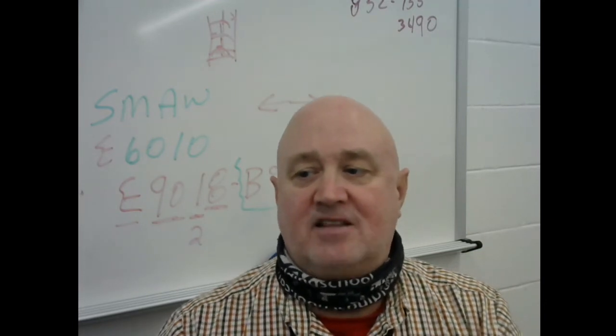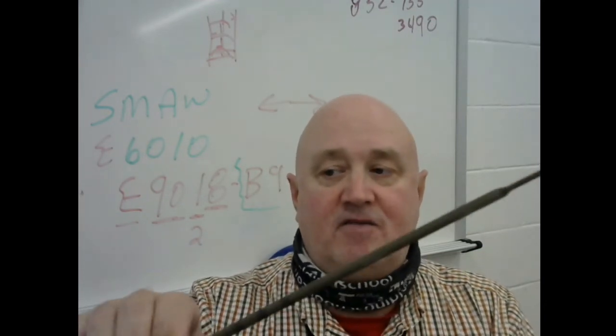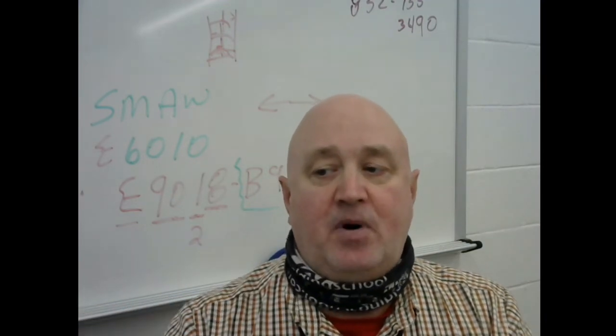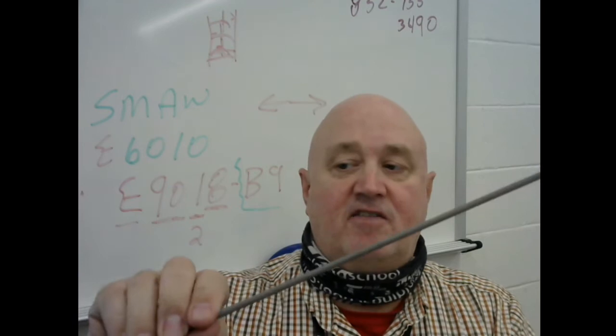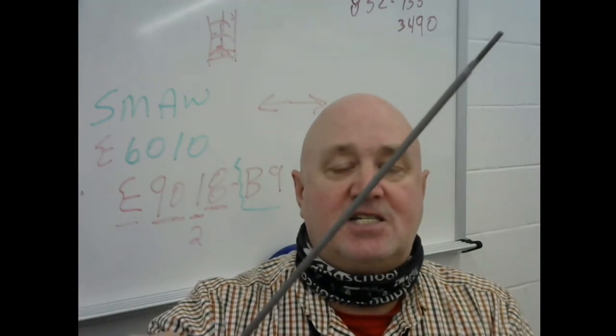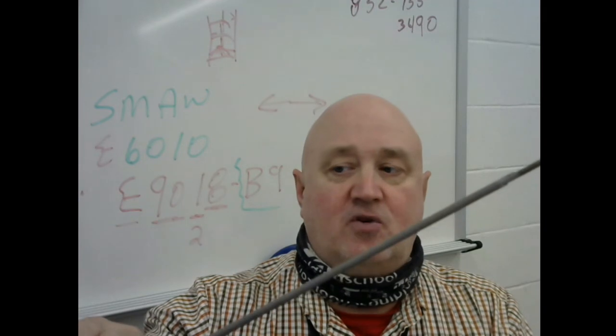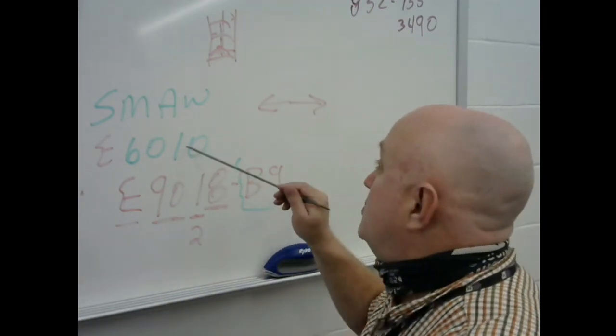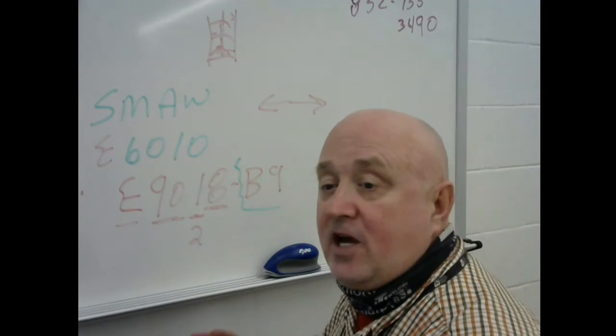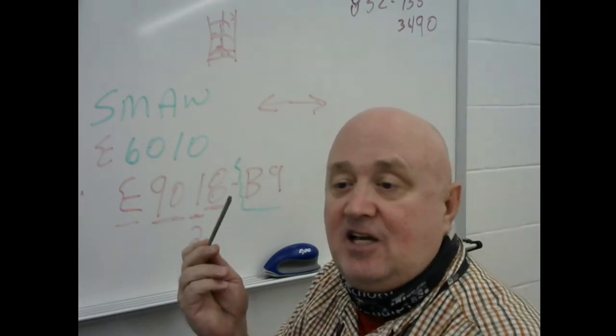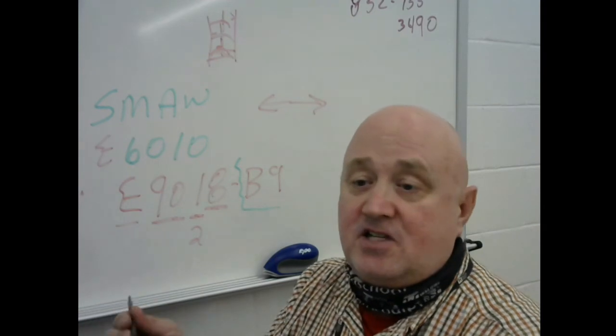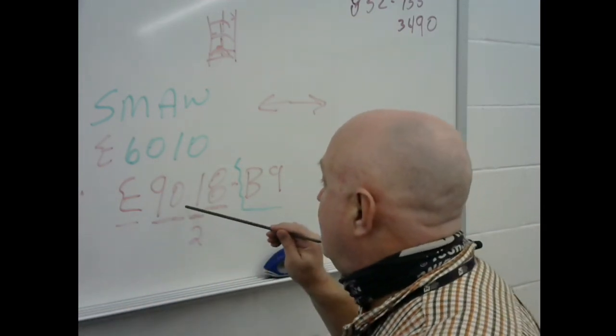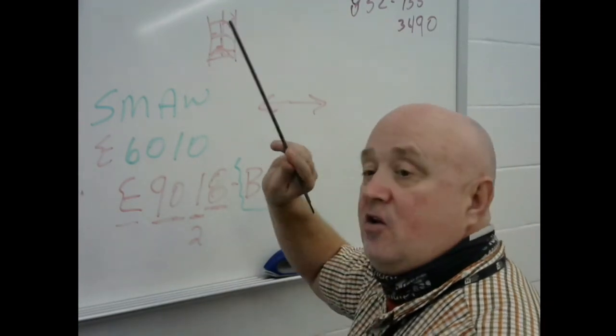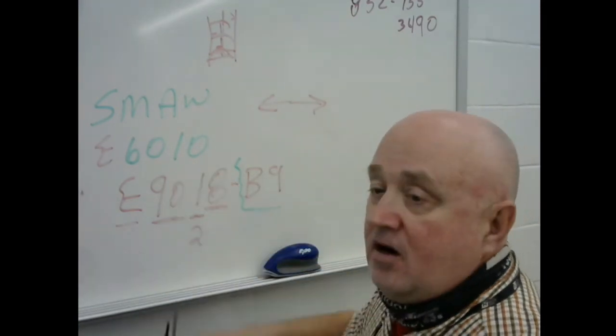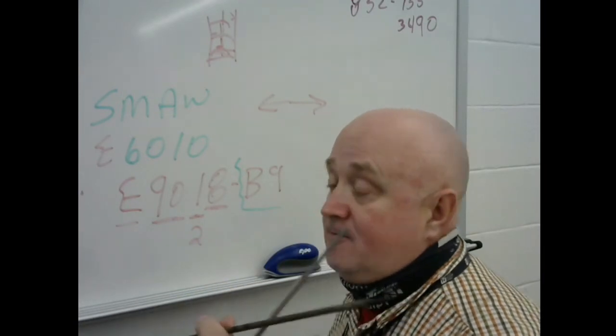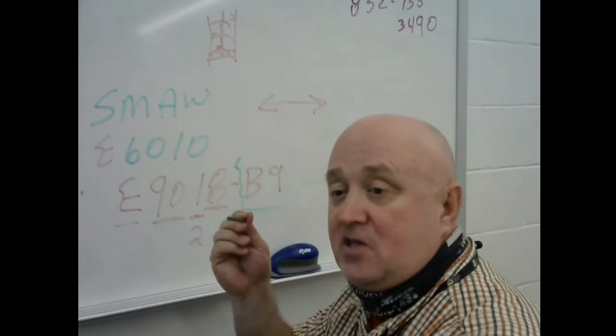It does a little bit like the 7024 where we've got some fast deposition, but it also has the characteristics of our fast freeze, which is 6010. 6010 has a fast freeze characteristic. That weld puddle, if I'm welding out of position, is going to freeze a lot quicker than something like a 7018, which is a fill freeze. And a 7024, there's no way in hell I can get it to run uphill, horizontal, or overhead, because I've got a 2 in there, and the 2 says it's flat. I can either weld flat or horizontal fillets with this guy.